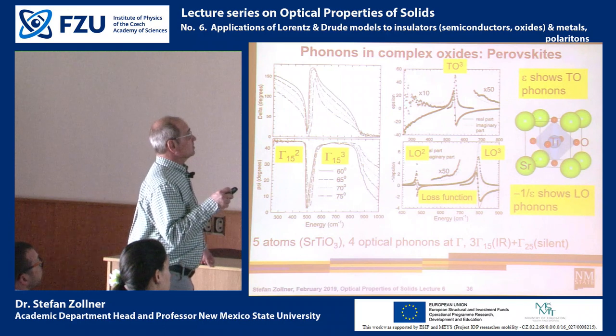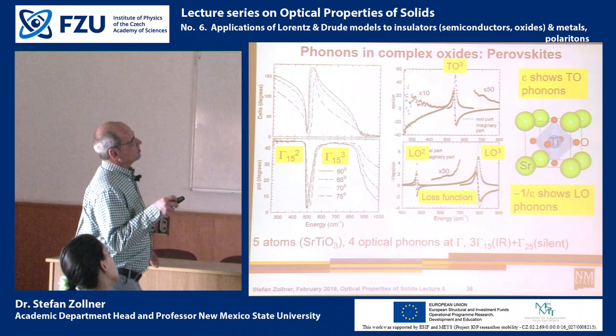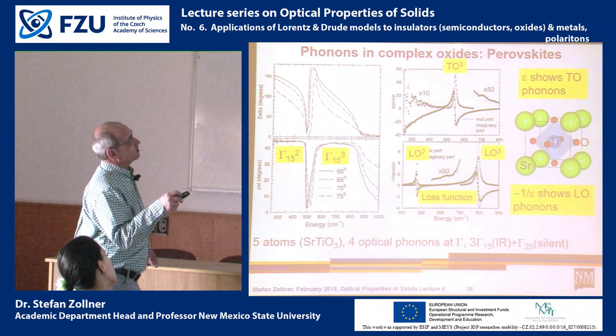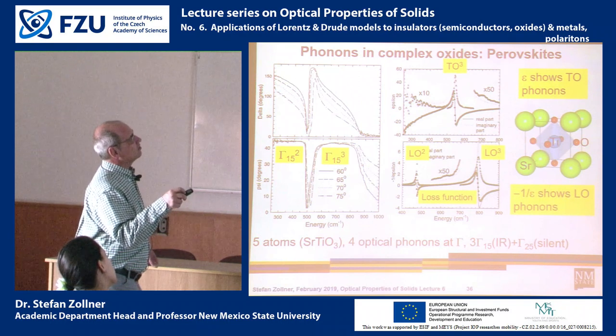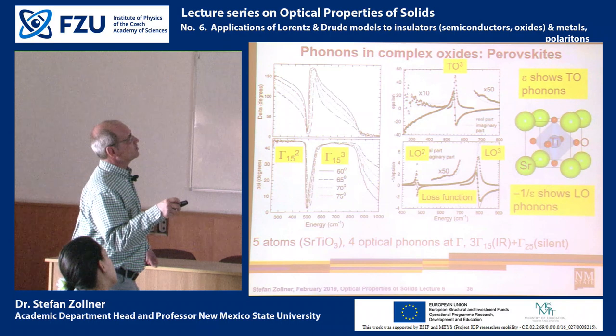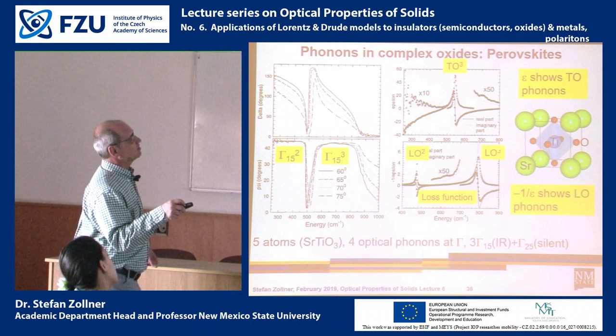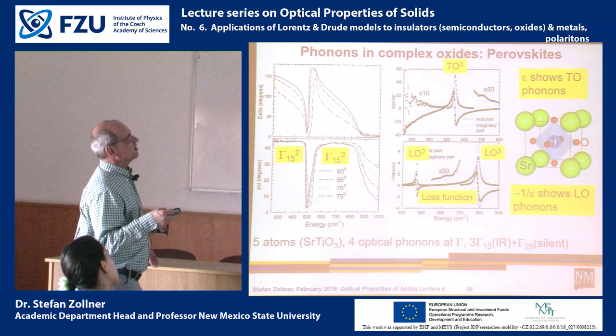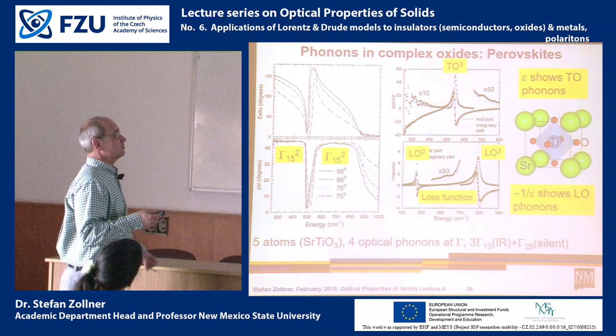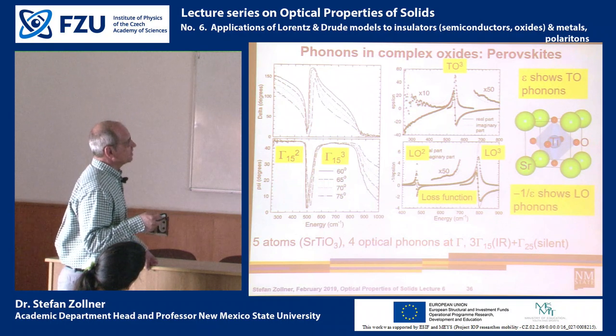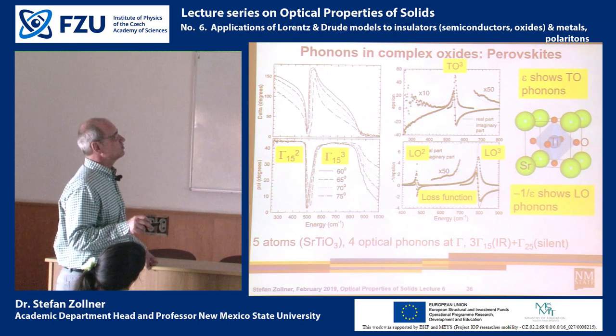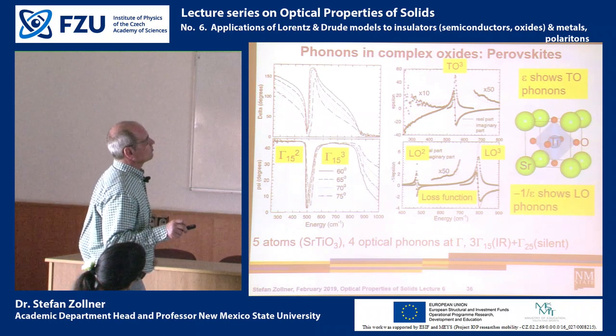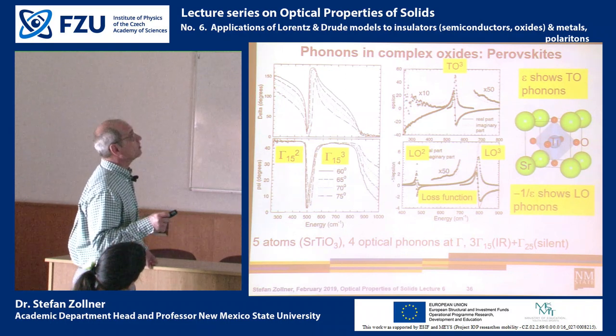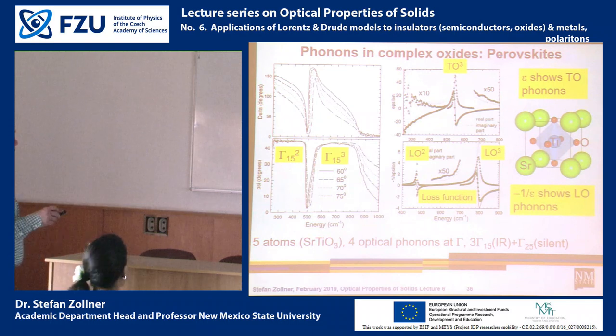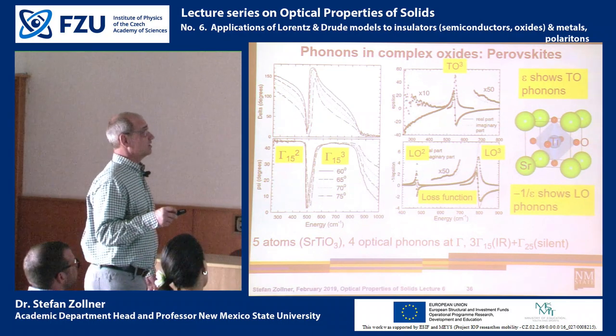And instead of showing this as psi and delta, we can also look at peaks in the dielectric function. So we see that third TO mode very well. And in the loss function, we see the second LO mode and the third LO mode. If we wanted to see the first TO-LO mode, the first vibration, then we would need an instrument that can measure lower than 250 wave numbers, which is possible. And there's a number of instruments that can do that, for example, in Brno.